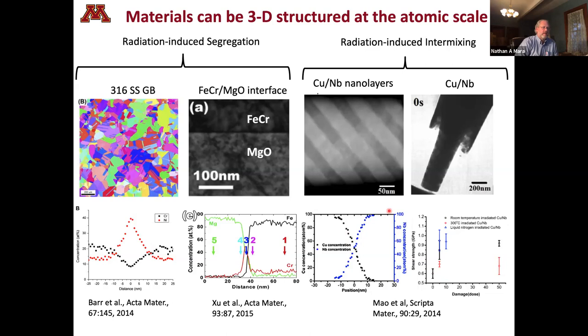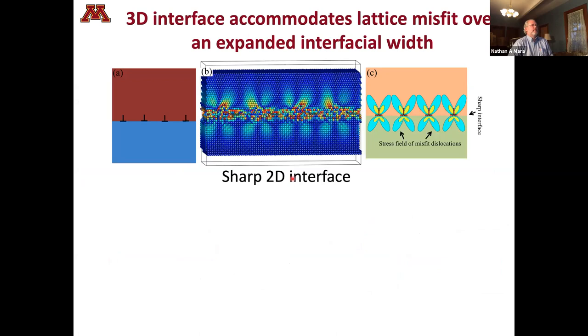So here's what we're doing. Here's the sharp 2D interface. You've got discrete dislocations, so four of them here. Let's put them in an MD simulation. Here's their 1, 2, 3, 4 dislocations, and they have stress fields associated with them, which kind of resemble these butterflies, right? And so that's a sharp interface. Those misfit dislocations relieve the immediate elastic strains at that interface.